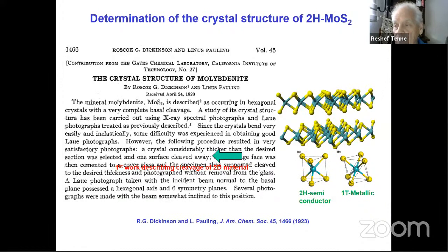He studied these materials first, and he found that they are very strange, that the C-axis is 7 angstrom, or 6 angstrom, as the separation between the layers. This means that there is no chemical bond holding the layers together. So he concluded that these materials have very anisotropic properties, and the chemical bonding in the layers in the AB plane is covalent, of course, between the molybdenum and, let me just present with the laser pointer.